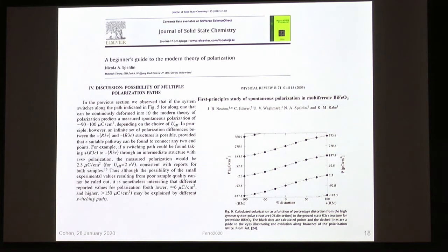But they point out some of the things that I'm talking about here. They say possibility of multiple polarization paths. So some of the things I'm talking about have already been intimated in the literature, so I can't really take credit for it. The thing is that it's possible if you don't know what zero is. So here is an example where you calculate the polarization as a function of distortion going from the ferroelectric bismuth ferrite to negative ferroelectric bismuth ferrite. And there's some path, and then you can calculate the polarization for each point along this path. The problem is, what's this path?